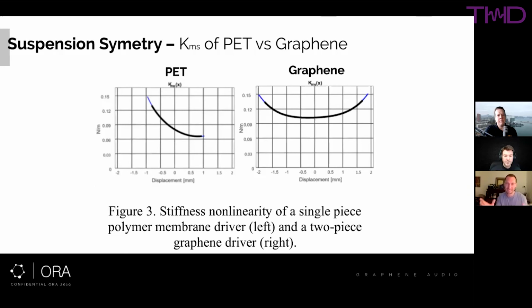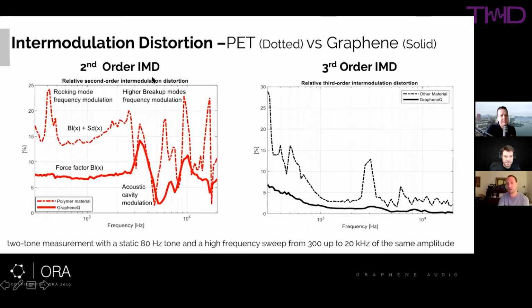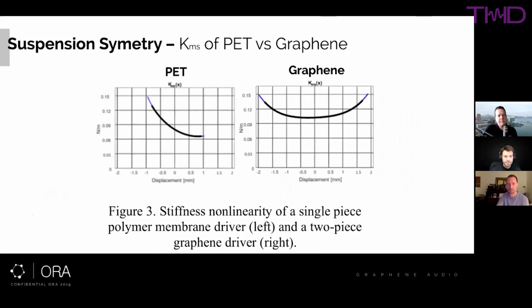But with the free edge design, since it creates a much more symmetric spring function, you can allow it to move further without getting a lot of that low frequency distortion. And when you start looking at this intermodulation distortion, that's part of why the graphene driver is so much lower, because it's not riding on a lot of this low frequency nonlinearity. That's basically a product of that nonlinear KMS function.